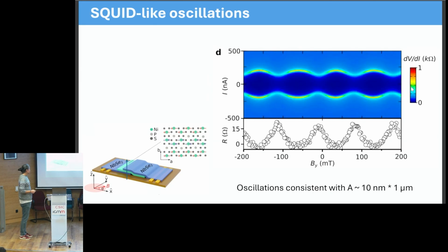So we do a measurement like that, and we apply a magnetic field perpendicular then to the flow of the supercurrent. And what we see is a quite different pattern, actually, a pattern that really resembles a superconducting quantum interference device. So to get a pattern like this, essentially what you need is that the supercurrent runs through two separated channels. And now when we apply magnetic flux, the interference will lead to this kind of oscillations. What is striking, I think, about this measurement is how clean and regular the discrete oscillations look.